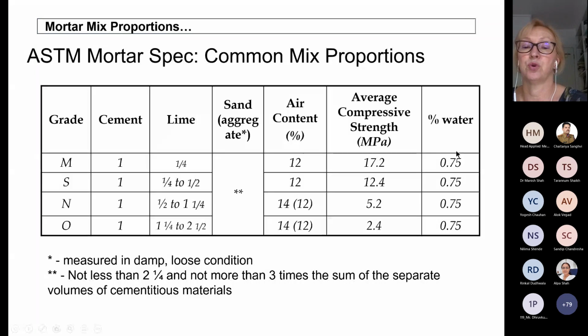And here is percentage of water. So this type S mortar, which is used for load-bearing construction, is 12.4. If you look at the type N, is much weaker, 5.2, and the weakest is type O, which is 2.4. Type O mortar is mostly used for historic structures where we have old mortar and we need to replace it by new. So that weakest mortar is used because old structures had also weak mortars. But for new construction, we use type S mortar in all cases.